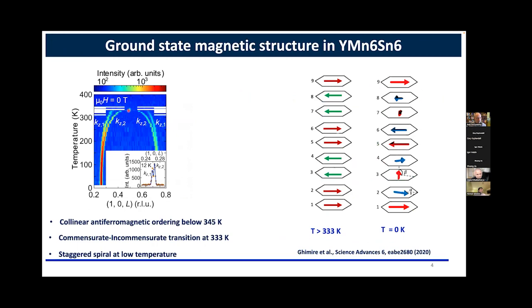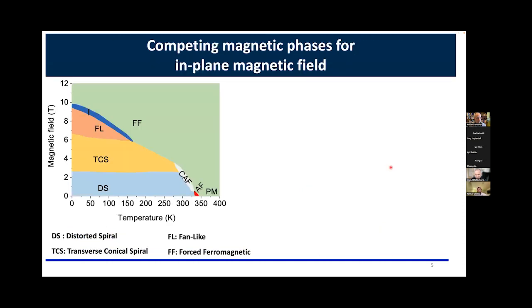It orders with collinear antiferromagnetic structures, as we can see here in the neutron data. And then as we cool down, J3 becomes important. It twists the spins, and then it gives rise to this spiral state, which we call the staggered spiral state. Now, when we apply a magnetic field within the plane, we can tune all these different interactions and drive a lot of different magnetic phases.